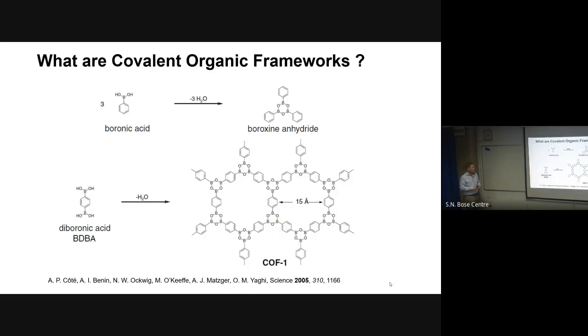So, what are actually covalent organic frameworks? The first example of a covalent organic framework was this one, published by the group of Yaghi in 2005. Essentially, you can imagine, if you remember your organic chemistry, I don't know how many have a chemistry background here, you can trimerize boronic acids by this condensation reaction, and then you get this boroxine anhydride ring. And if you imagine that you have a ditopic boronic acid, same type of condensation reaction, you can form a framework with a lot of these boroxine anhydrides, which are bridged by biphenylene.